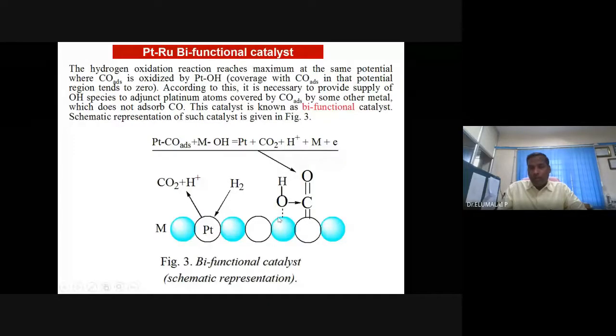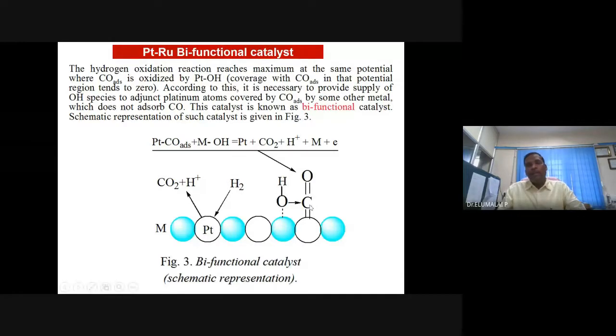On the co-catalyst site, OH or water can be adsorbed. When it adsorbs, a metallic bond is formed between the platinum and the co-catalyst, which can be titanium, tin, ruthenium, molybdenum, etc. When it does so, the bond strength between the platinum and the carbon is weakened, so that the formed CO can be easily decomposed. Once the CO is decomposed to CO2, a fresh platinum site is available so that a fresh methanol molecule or ethanol molecule, or if it is a hydrogen molecule, can be adsorbed and continue oxidation.